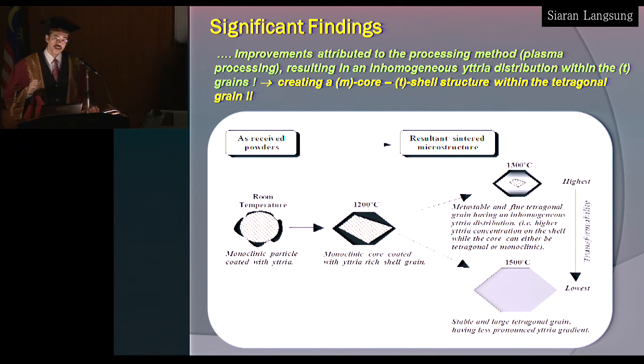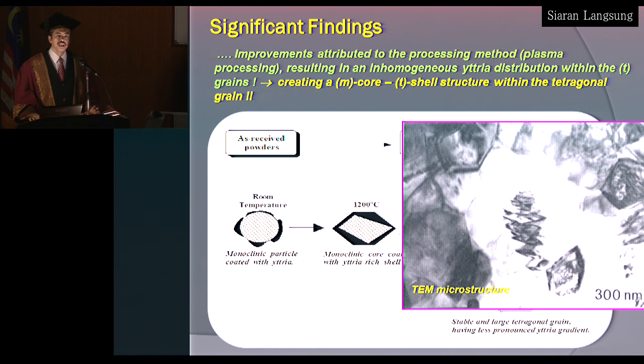And of course, further increase in temperature causes more diffusion of yttrium, the stabilizer, into the structure, and therefore it also induces grain growth. Now, through transmission electron microscope, we found evidence of a coring effect, as I mentioned, a tetragonal-monoclinic core structure, where at low temperature, the core of the tetragonal grain is still in the monoclinic form, but the shell is in the tetragonal form. The core is monoclinic, the shell is in the tetragonal structure.